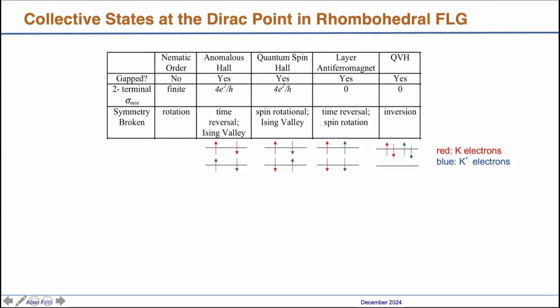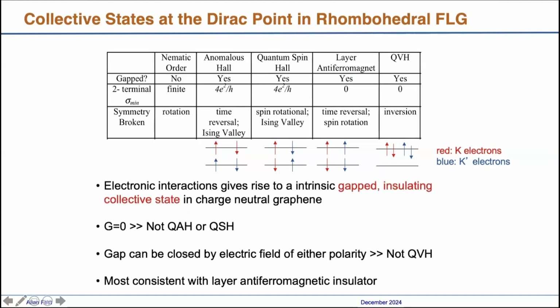Theoretically, these are the possible states. Basically, you have spin and valley, and then you have 2 layers. How do you put the different spin and valley on the layers? This will give you either an anomalous Hall state, a quantum spin Hall state, or a layer antiferromagnet. So what our results show is a gap insulating state.